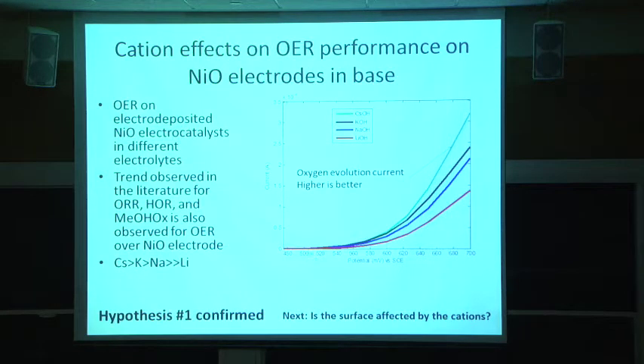And you can see here the lithium is, again, the least active, and cesium is the most active. And over here, there's something like a factor of 2 difference in activity. So just by changing from 0.1 molar lithium hydroxide to 0.1 molar cesium hydroxide, we can double the activity of a straight nickel oxide electrocatalyst.